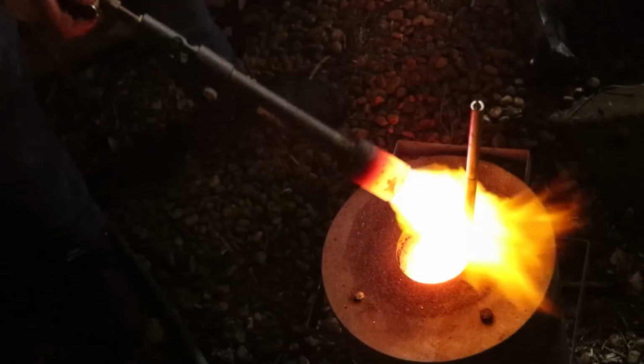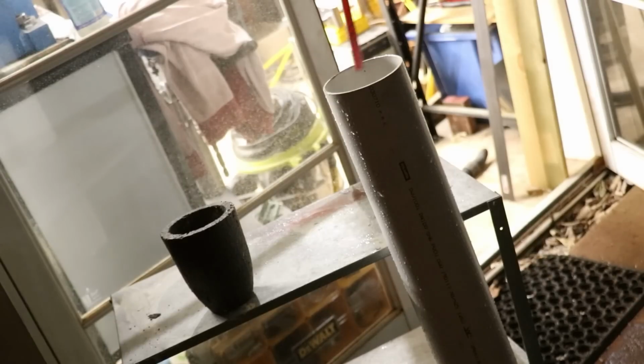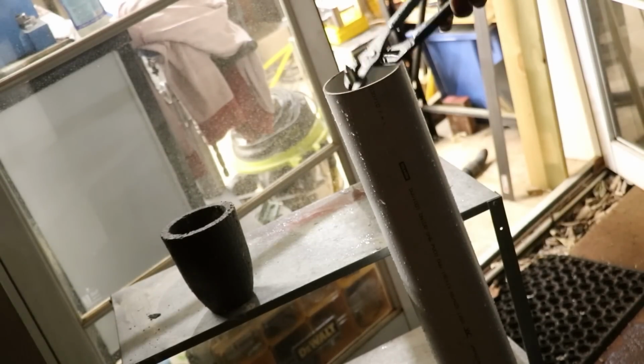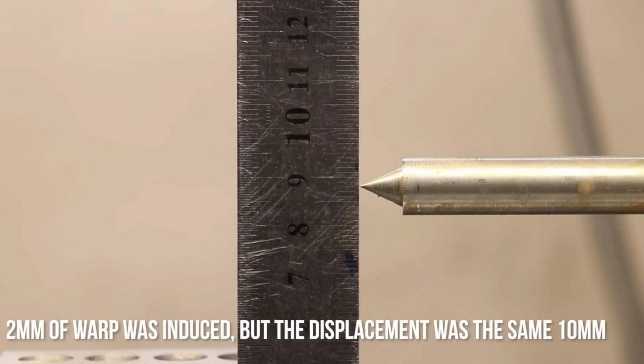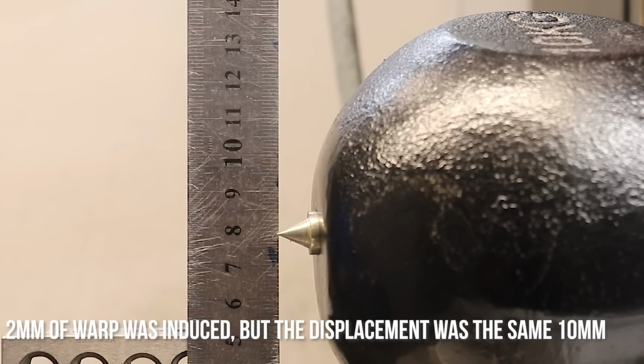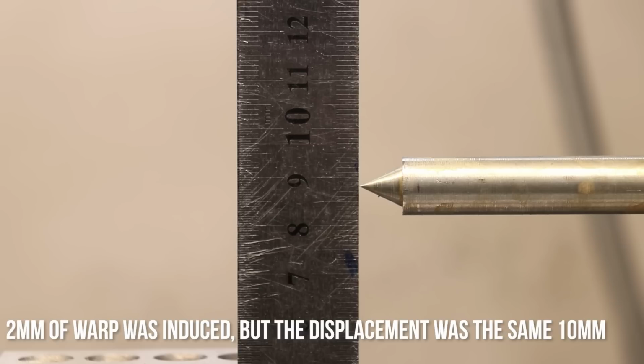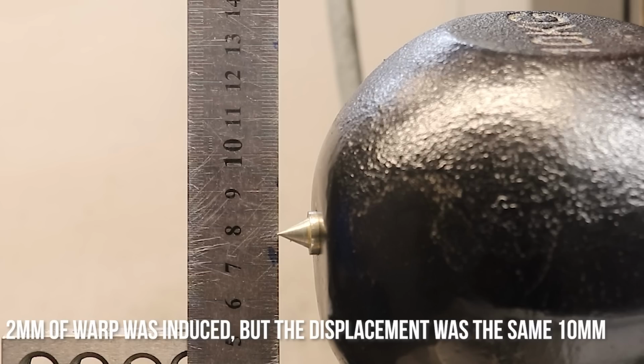I then took it to the furnace and heat treated it to the low 50s Rockwell C hardness, and once the weight was put back on, the sag over 45 centimeters was 10 millimeters. It was exactly the same as it was before. Unfortunately, with it being heat treatment, the part warped about 2 millimeters over the span of 45 centimeters. Not perfect because it will change the shape of the part that we're testing, and that does change the spring constant ever so slightly. But I don't think it was enough to really throw off the results.